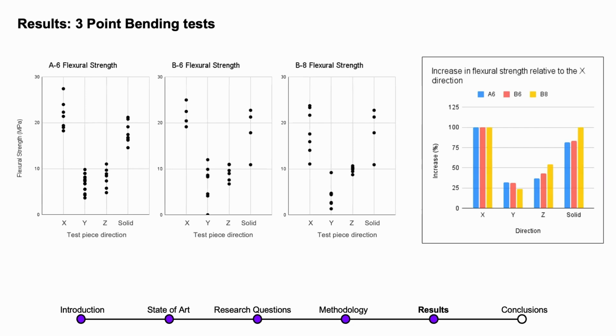We see that for the three-point bending test, the behavior is much different. If we take 100% for the X direction, the resistance in the Y direction is almost a third, and almost the same for the Z direction. Even the solid test pieces are weaker than the 3D printed ones in the X direction.